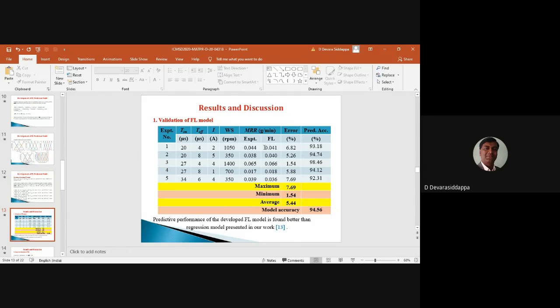As you can see, the fuzzy logic model predicted with better prediction accuracy. The maximum error in the prediction was recorded as 7.69%, minimum as 1.54%, and average value is 5.44%. The model accuracy, based on these validation data sets, is recorded as 94.56%. And this is compared with our published work of the regression model. We found that this fuzzy logic model prediction is better than the regression model prediction for the same data sets, for the same MRR calculation.